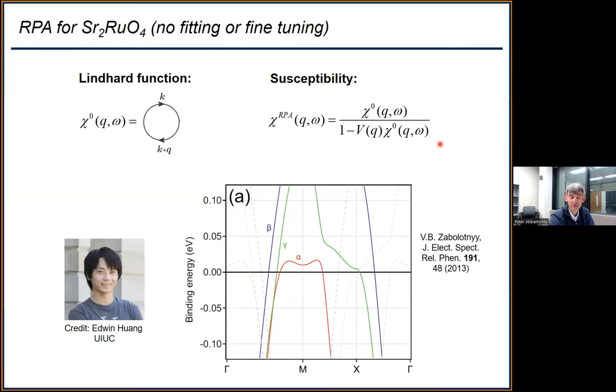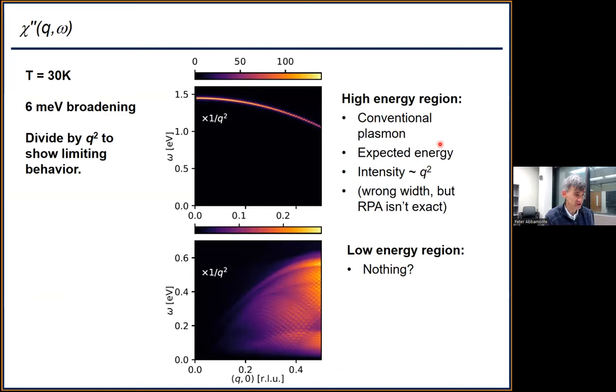The only number that you have to put in is epsilon infinity, which is 4.5. Even that's known. So there's nothing to fit. You just plug it in and then see what you get. We thought, okay, let's see if you get, well, first of all, a normal plasmon, and then let's see if you get a demon. So this is the first result.